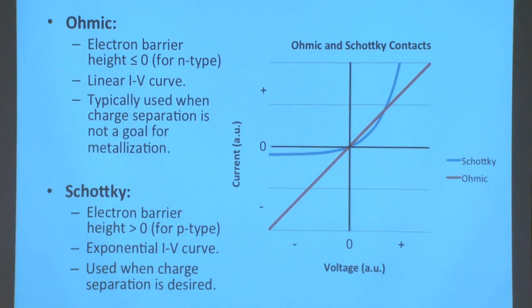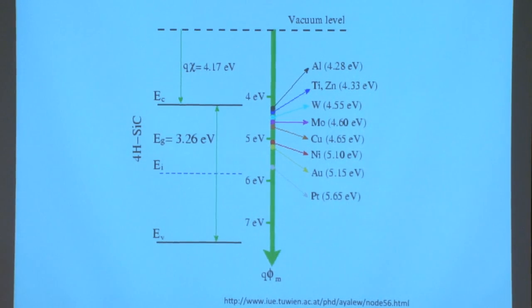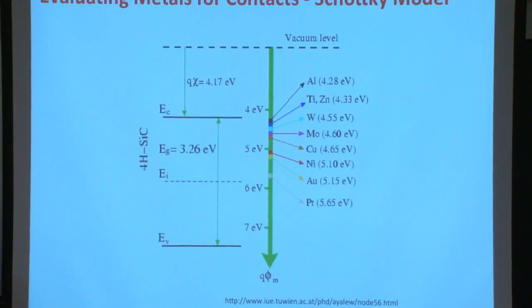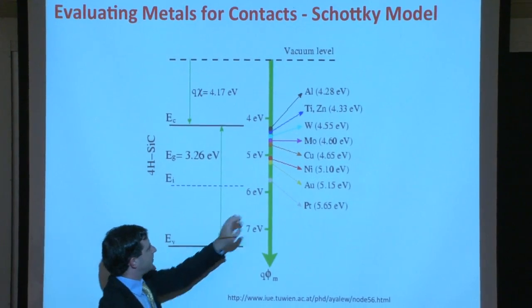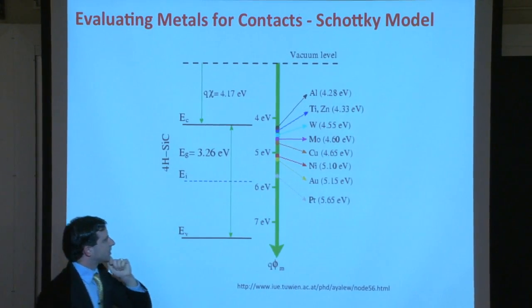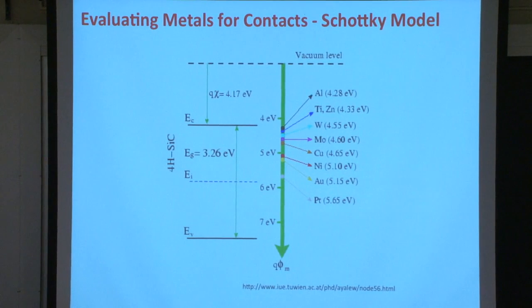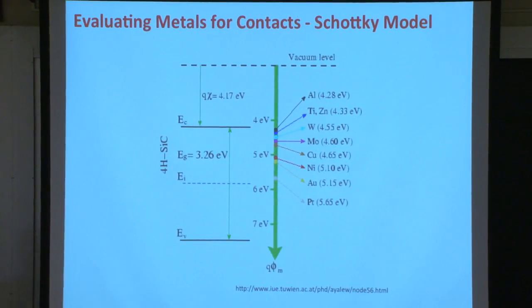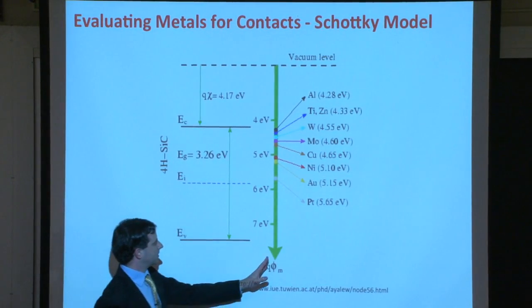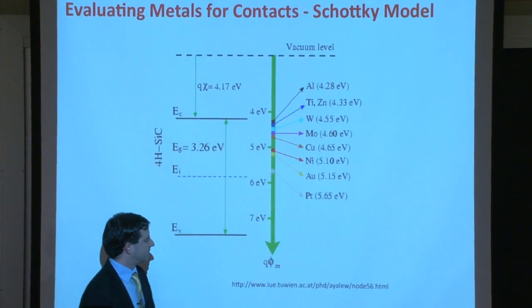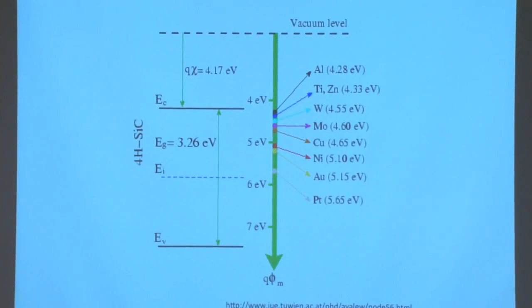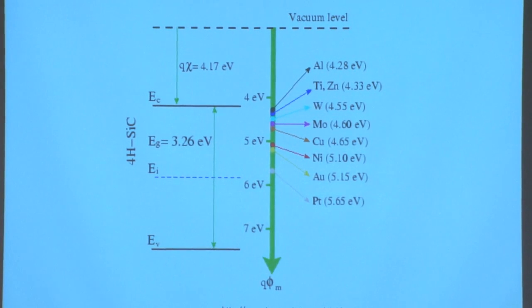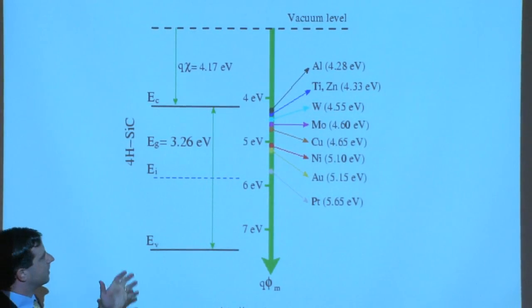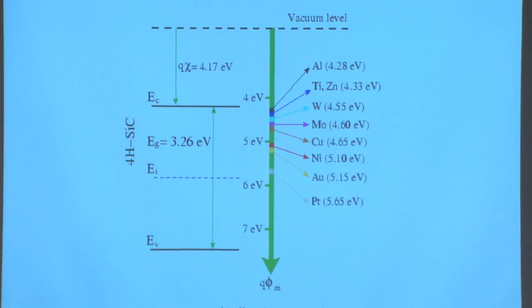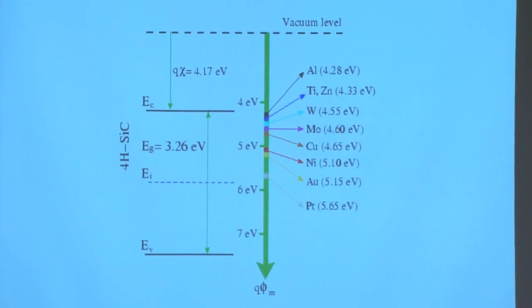In that particular case, the natural question is, what metals should we use, or what is the range of metals that are available? If the barrier height is a function of the work function of the metal, what is the range of work functions that are available to us? On this green arrow right here, which is Q times the work function of the metal, we have a range of different metals from aluminum to platinum, and titanium, zinc, tungsten, molybdenum, copper, nickel, gold in between. And of course, there are other metals too in the periodic table that you can add to this chart.